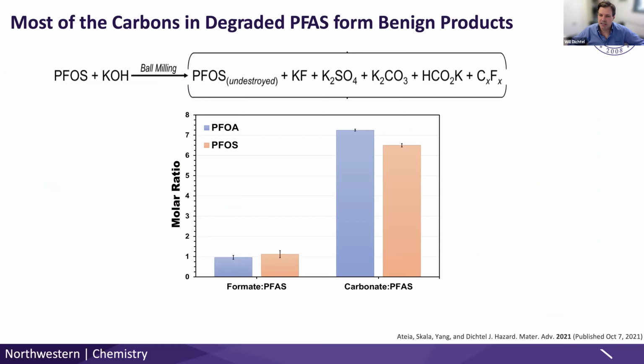Ultimately, by looking at this reaction very closely, Moha discovered, first off, that ball milling looks pretty good. We can completely destroy PFOS. We get 1 molecule of formate out. That's pretty benign. The rest of the carbons seem to come off as carbonate, which is also a benign ion. Sodium carbonate is just washing soda. So it's essentially turning this stuff into CO2.